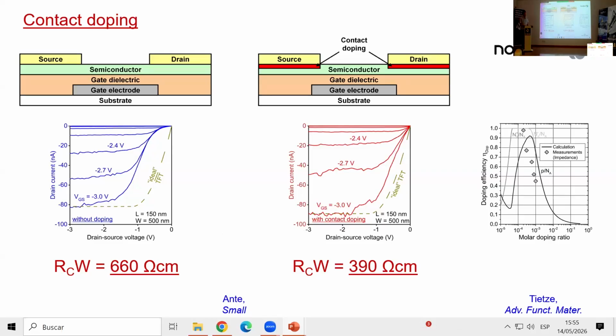So yeah, absolutely. In silicon MOSFETs and in basically any type of inorganic field effect transistor, the contact resistance is basically at the quantum limit. So as small as it can ever be. That's about 1 milliohm centimeter. Only in organic transistors is the contact resistance still, even in the best organic transistors, orders of magnitude above the quantum limit. And the main reason is that we are not doping. Now, of course, we tried doping many years ago.